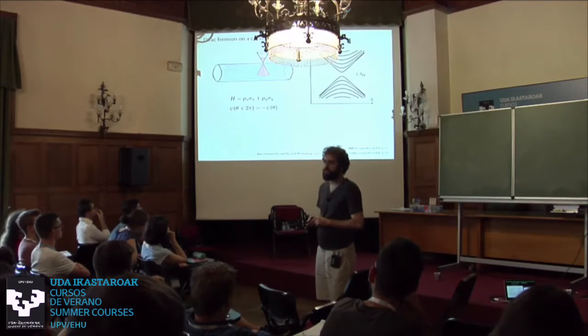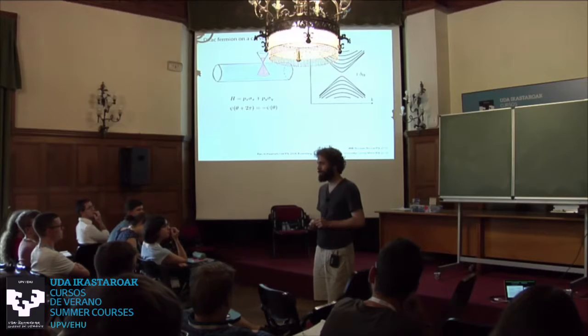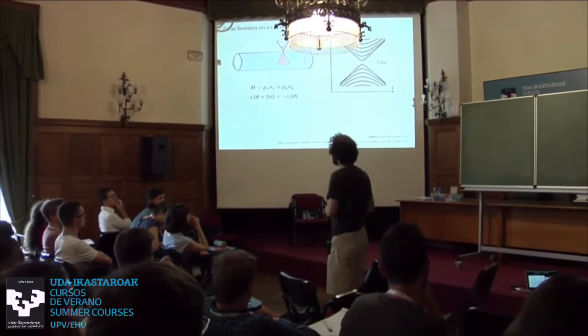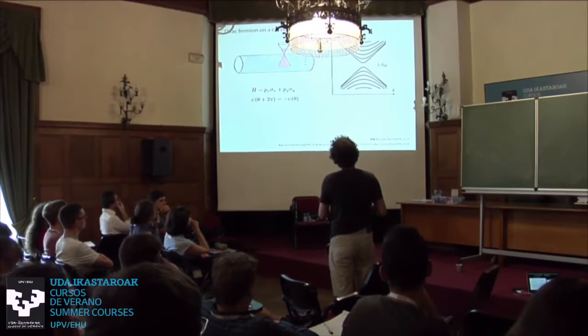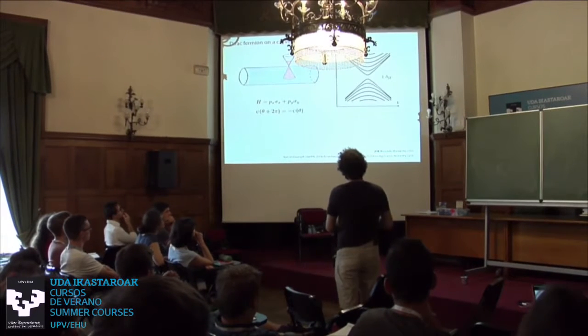Now, why is this surprising? Well, because everyone, since you were a kid, has told you that topological insulators are characterized by a surface which is gapless. But actually, if you take a topological insulator and make it into a wire, you get a gap.